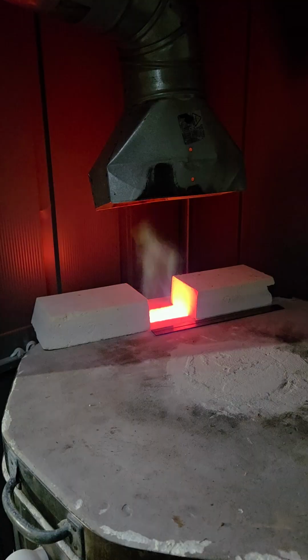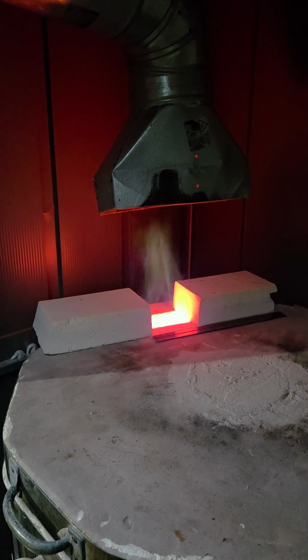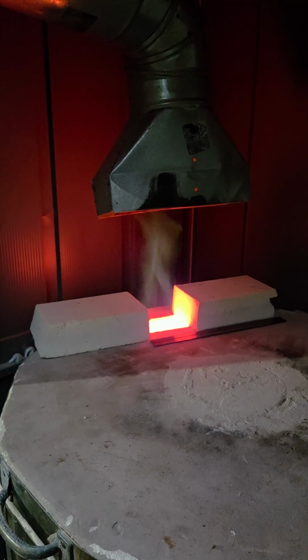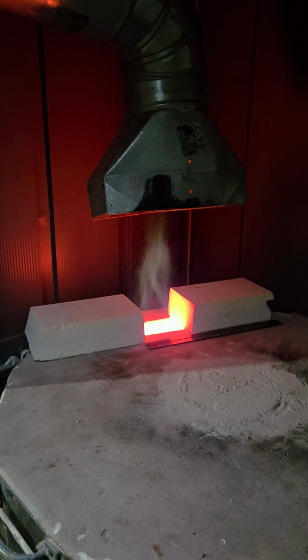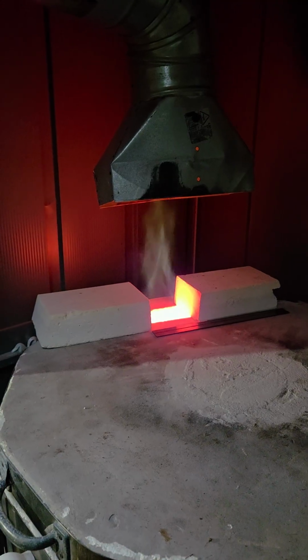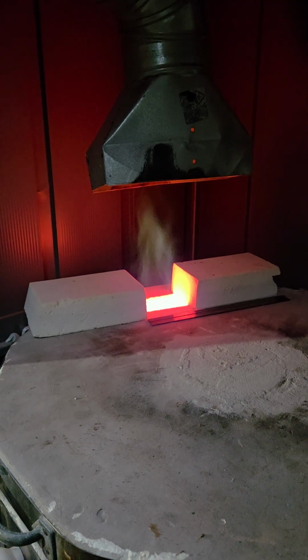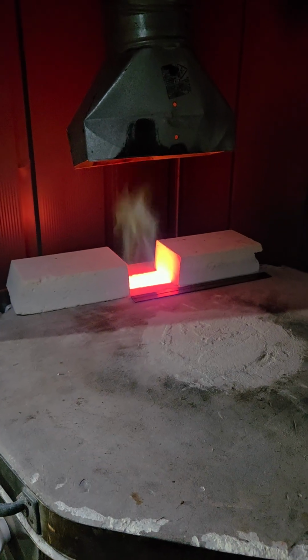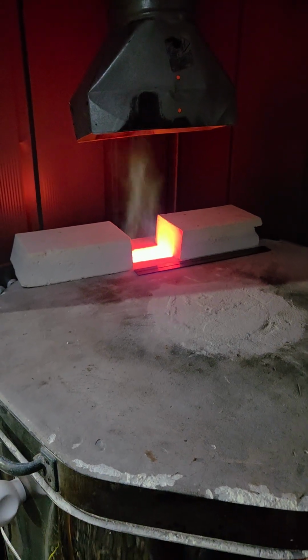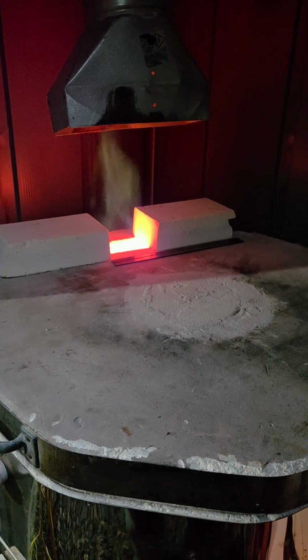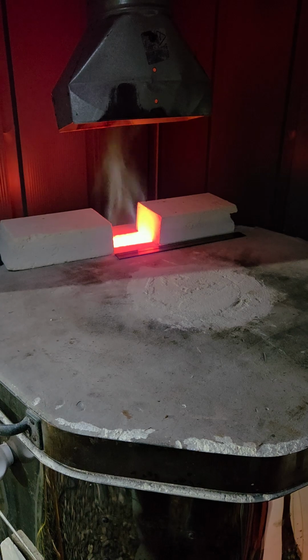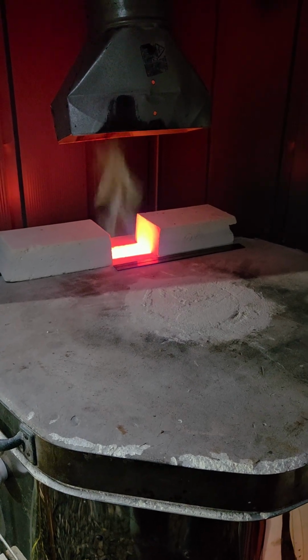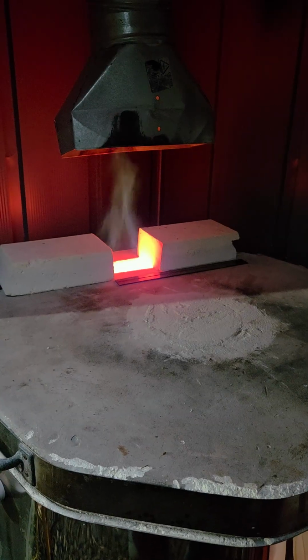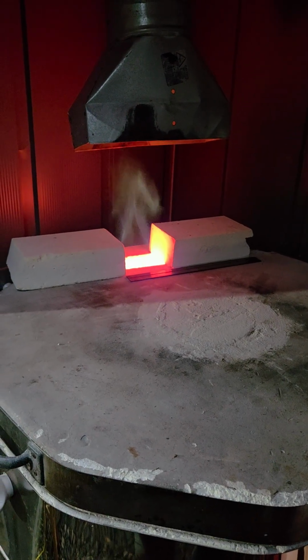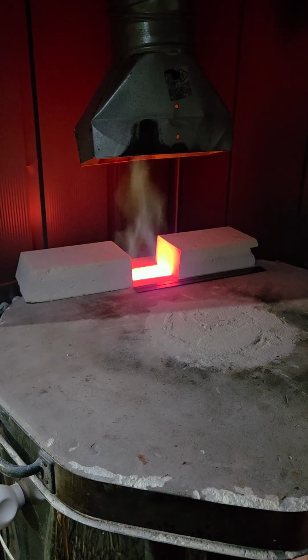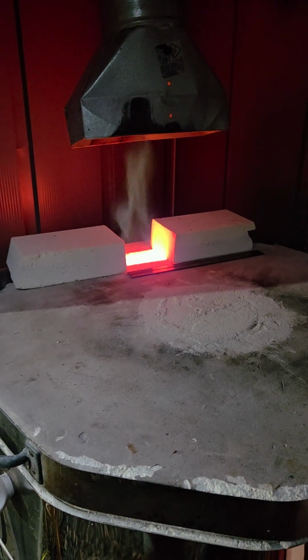Typically when it gets up to about 1150 to 1180, it'll slow back down to 100 degrees per hour, and I will go ahead and open it up again there to maybe 4 1/4 inches. So I've got a few more minutes to go until I make that adjustment, and the pressure remains constant. I'm not going to go any higher than 2.2, and 2.2 does do strong reduction on this kiln. 2.1 is better for just a mild reduction, and that way it won't blow out celadons and rutiles.